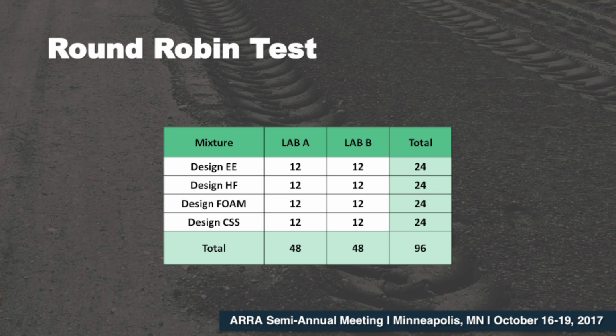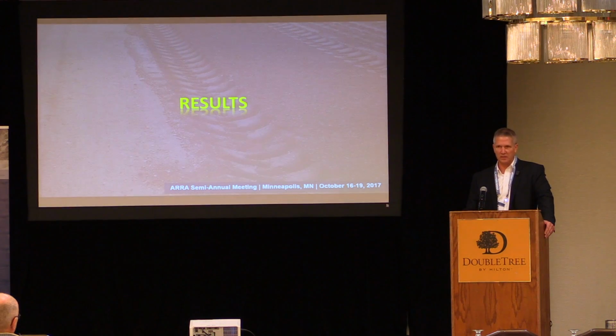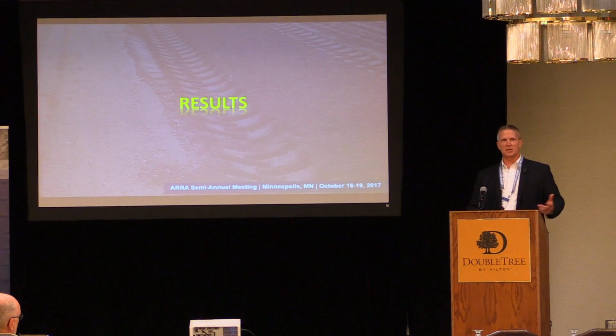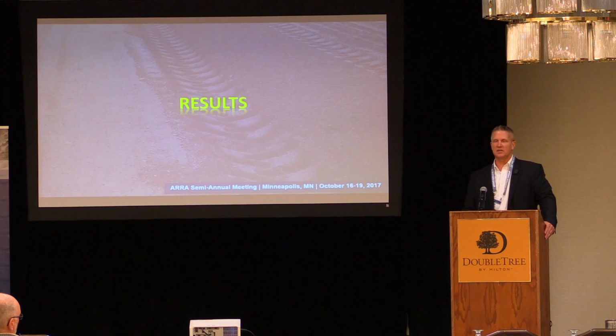One of the things that we also did was a round-robin test between the two labs. That would be Braun Intertech and American Engineering, which we then took the samples that were produced in the mixed design phase, did an awful large number of sample set, 96 samples total, to look at round-robin and interlab correlations. You might ask, why am I spending so much time on the aspects of this test?